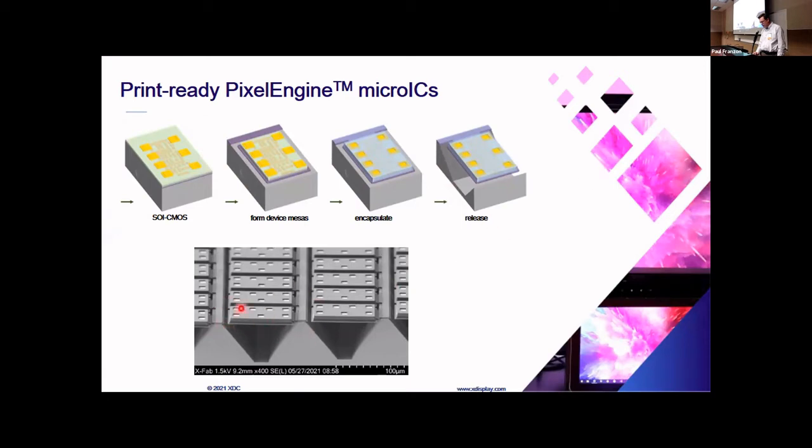Ultimately, what you end up with are very thin, small micro ICs that are undercut. They're held on with a tether and anchored to the substrate via this line of material here. And so these are ready to be picked up and transferred with very high yield to the display backplanes. This device, for frame of reference, is approximately 90 by 50 microns by about 10 microns thick.